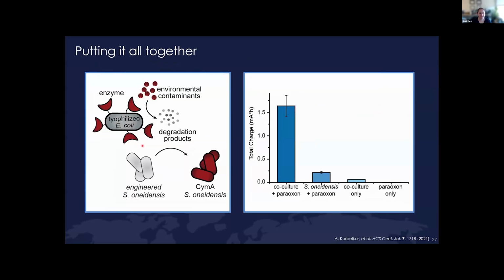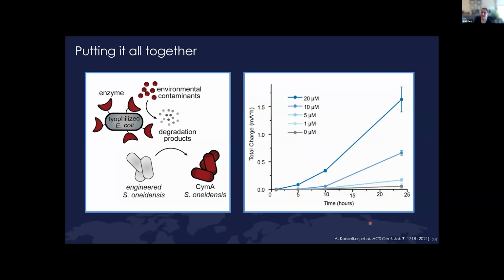And normally, these Shewanella would not like to live in the same environments as E. coli. But if you remember, we've already freeze-dried our E. coli and killed them. So we can mix these enzyme materials with our Shewanella to basically get one-pot degradation and detection. And if we look at the right here, we see that this has very high specificity for both of those microbes plus the full pesticide. We do see a little bit of background expression, which we think is from the degradation of the pesticide through UV light exposure.